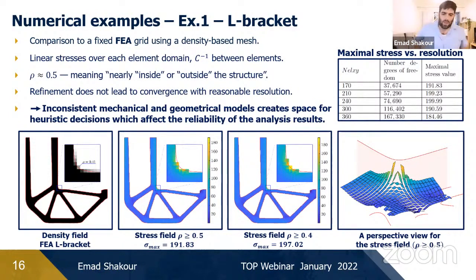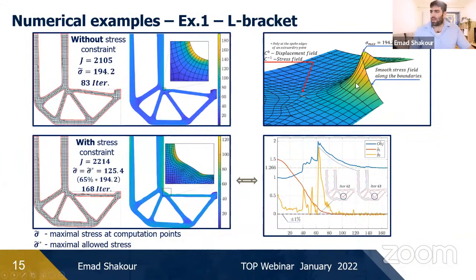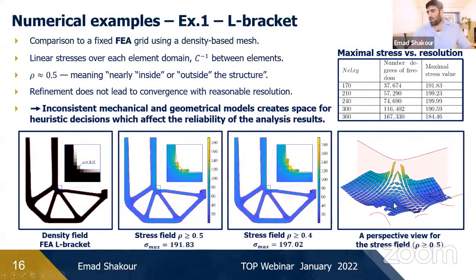We could see the stress field at the stress concentration region in the rightmost figure. And of course, we could compare it with the stress field from the isogeometric analysis in the previous slide. Here we could see, from the previous slide, the stress field in the isogeometric analysis, which is C1 continuous near the boundaries. And here, according to C0 finite element analysis, we get a stress field of C-1 continuity.